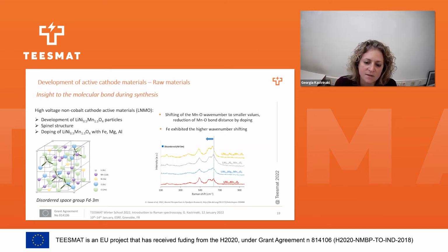So what happens is that the iron exhibited the higher wave number shifting. So this means that while trying to substitute nickel in this lattice, we had a shrinkage, let's say, of this molecule. And what we saw is that it turned out to have better stability of our material during high cycling and high voltage cycling.